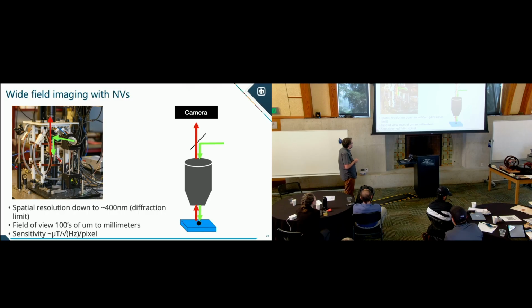And so this gives you spatial resolution down to the diffraction limit, so 400 nanometers. The field of view of this can be hundreds of microns to millimeters, and the sensitivity then is microtesla per root hertz per pixel. So, many orders of magnitude less sensitive than other quantum sensors, but really giving you this spatial resolution to look at interesting things at these length scales, and we'll talk about that here shortly.